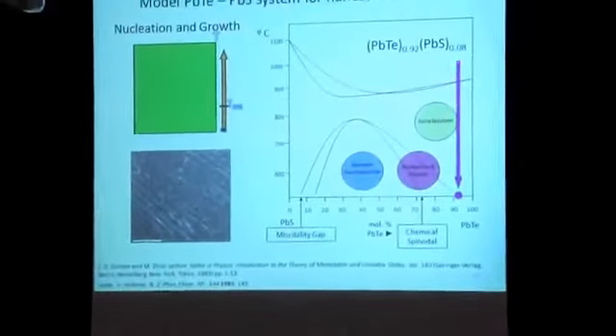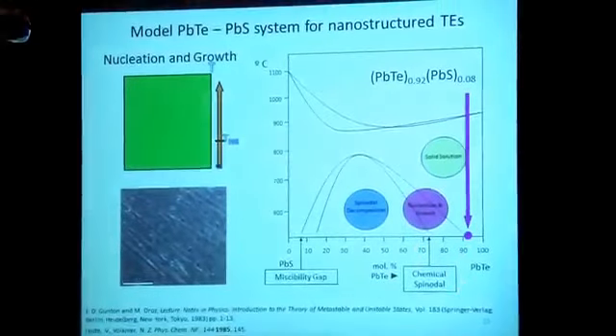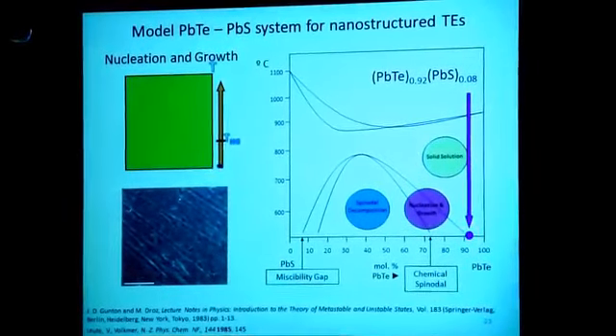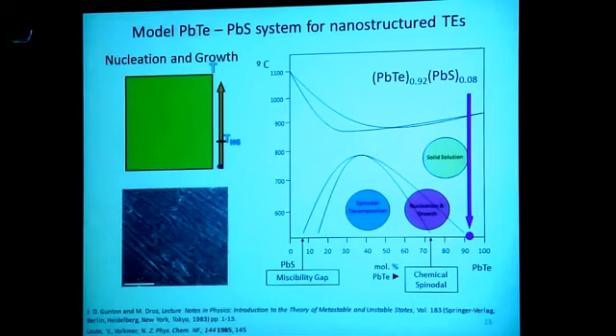We managed to quench a melt from here, from the liquid down to the solid state down here, and show that it was a solid solution. It didn't have time to phase separate. We analyzed it by TEM and found no evidence of phase separation. However, it's metastable because according to the phase diagram, it should be in the nucleation and growth region.